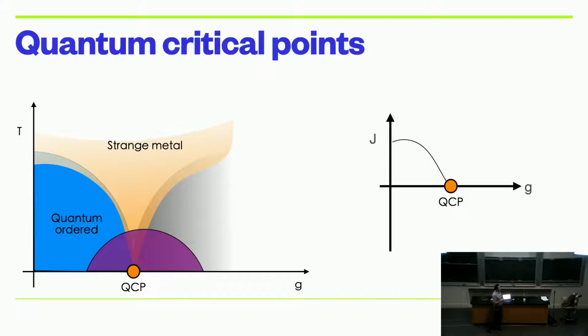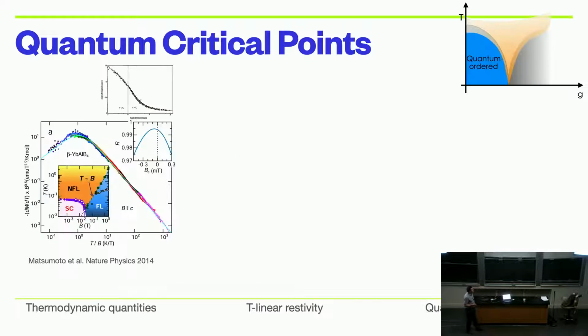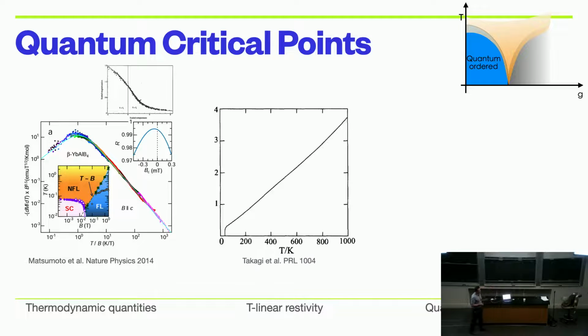So people from the very early stages of studying unconventional superconductors started to think that maybe quantum criticality had something to do with the existence of the superconducting dome, of the superconductivity itself. Okay, what are the weird properties that come up? Well, you get lots of interesting scaling behavior that again come up from the scale invariance of the system. In this case, I've got this one unconventional material where the magnetization shows a collapse of all the data. There's this appearance of what's known as T-linear resistivity. Unsurprisingly, it's where the resistivity is linear in temperature. And that's seen over and over again in lots of unconventional superconductors.